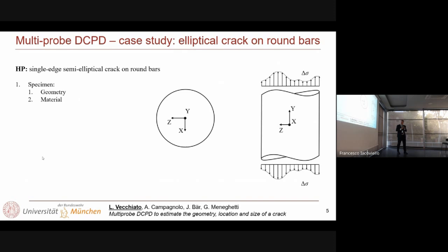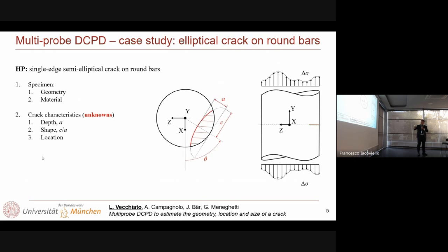Just limiting the problem for this application, for this case, just consider round bars subjected to mainly axial loading. Just to keep stuff simple, consider the case of one semi-elliptical crack propagating from the edge of the specimens. In this case, we have at least three unknowns, which are the angular position of the propagating crack, the crack depth a, and the shape of the crack described by the aspect ratio c over a. So these are our three unknowns.